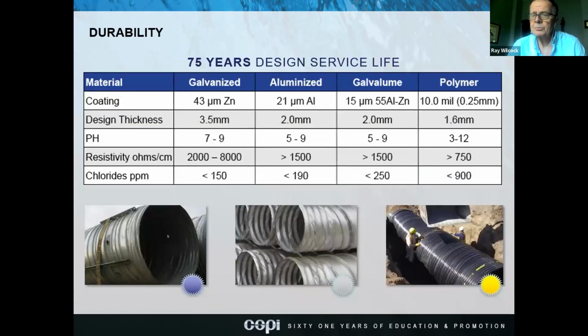With regards to durability for corrugated steel pipe, we've done extensive testing for the last 30 years to come up with a chart with regards to how long does it last and what type of environment. So we have galvanized, aluminized, galvalume, polymer laminated, and then we have 75-year design service life. And if you look down the side, you'll see the coating of those particular materials, like galvanized 43 micron zinc coating. Design thickness, 3.5 for galvanized, going down to 1.6 to polymer.